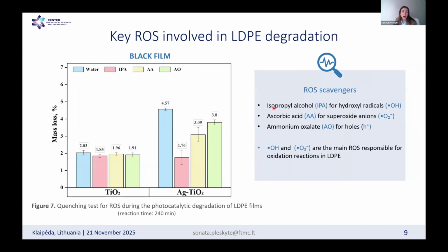And finally, we also evaluated the reactive oxygen species formation, and for this reason we performed a quenching test using reactive oxygen species scavengers, which are presented in the slide over here. And we found that hydroxyl radicals and superoxide radicals are the main reactive oxygen species responsible for the successful degradation process. And you can see from this graph that the hydroxyl radical had the biggest contribution to the photocatalytic degradation reaction. This could be related to the high hydroxyl radical redox potential, which is approximately plus 2.8 volts.